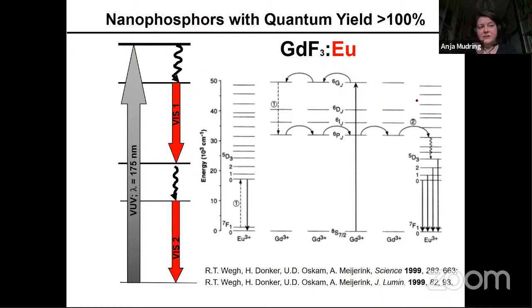You excite the gadolinium, then you have energy migration through the lattice until you hit 1 europium ion that sends out a red photon. Then you de-excite your gadolinium to a lower state because of the energy transfer. It can activate a second europium ion and you get out the second red photon.